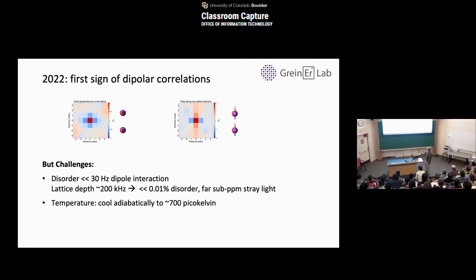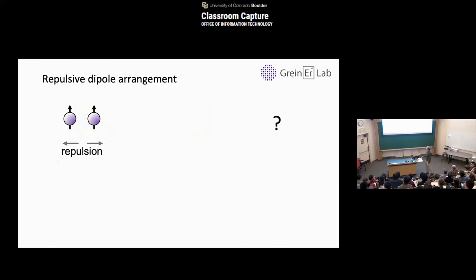So the big question was, can we go close to the ground state of the system? And just to show you how hard this is, this disorder needs to be much less than 30 hertz, right? Because 30 hertz is our dipole energy, so the disorder needs to be much less than that. But that means in a lattice depth of 200 kilohertz, you need to have less than 30 hertz disorder. So you need less than 0.01% disorder. So you have to be very careful that your laser beams don't scatter at the windows, all kinds of things like that, to get into this regime. And then the temperature, right? At 5 hertz tunneling, you need a few hundred picokelvin temperatures, essentially. Is that possible? Well, the idea is that as you reduce tunneling adiabatically, you actually adiabatically get to these low temperatures. So let's try it out.